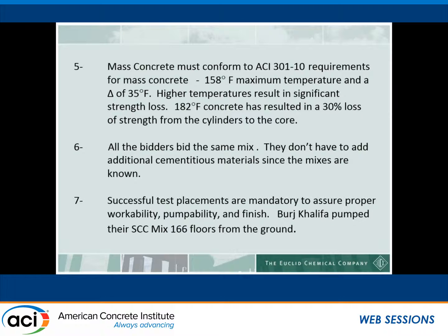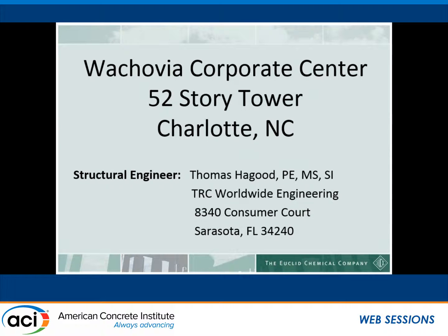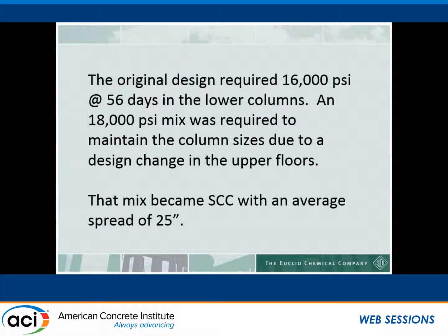Successful test placements are mandatory to assure proper workability, pumpability, and finish. The Wachovia Corporate Center, designed by structural engineer Thomas Hagood, is 52 stories. The original mix design required 16,000 PSI at 56 days, but an 18,000 PSI mix was required to maintain column size due to a design change in the upper floors. That is the mix that evolved from an 8 to 10-inch slump requirement into an SCC mix with an average spread of 25-inch diameter.